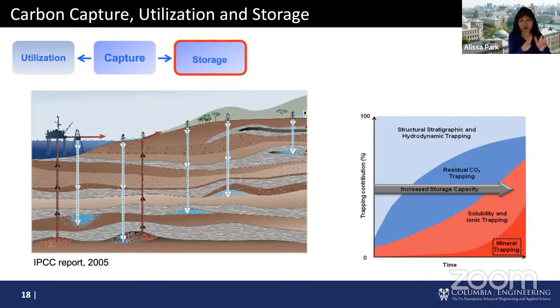And what would happen, the pressure and condition of CO2 being injected is about 150 atmospheric pressure. And as you inject, as shown in the right-hand side figure right here, it goes through 3 or 4 different trapping mechanisms, starting from having a strong cap rock, non-permeable cap rock. You're kind of keeping them as a plume, and this high-pressure CO2 now goes into the pores and then starts to dissolve in the water layer, and that's what happens over the years.